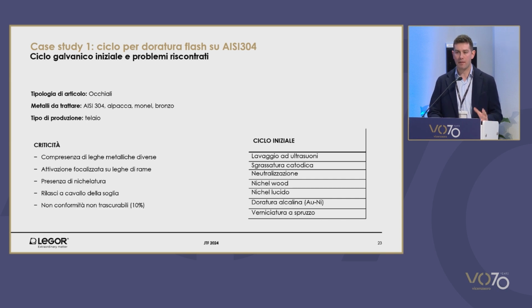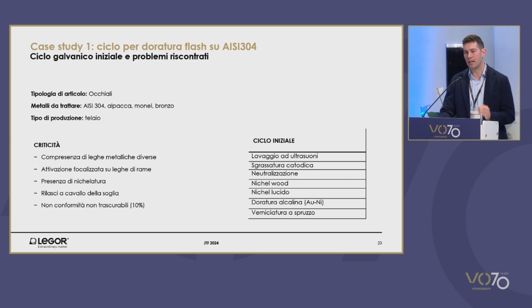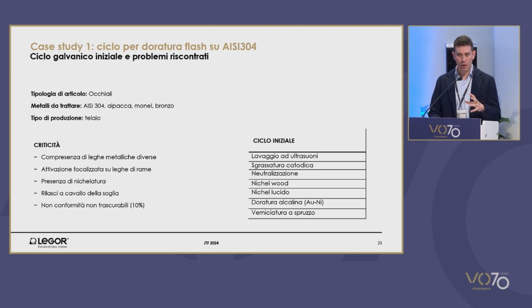10% of the production failed the test in terms of nickel release, and the samples with a smaller release were very close to the threshold limit, if not exceeding that limit. And those would be accepted because the regulation allows for higher percentages of nickel being released. It is not too restrictive.